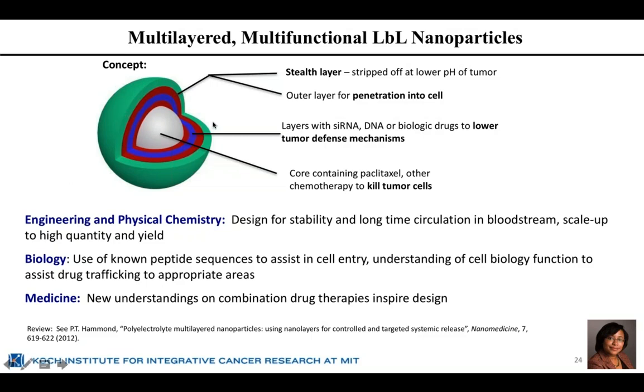Finally, we need to get this nanoparticle to distribute through the bloodstream. It's a systemic exposure that requires that the nanoparticle not carry positive charge, because positive charge will engage with the cell membranes of many of the cells in the bloodstream. So we're going to wrap it with a negatively charged nanoparticle, and we'll choose one that has a great relationship with water, because we want this to be a stealth layer that carries a large number of bound water molecules to it so that it does not tend to essentially attract the attention of the monocytes, the immune cells that travel in the bloodstream.